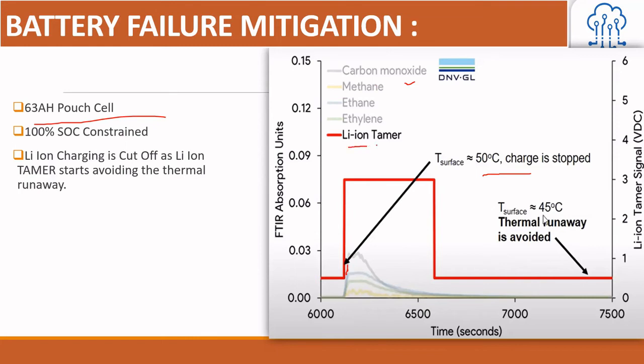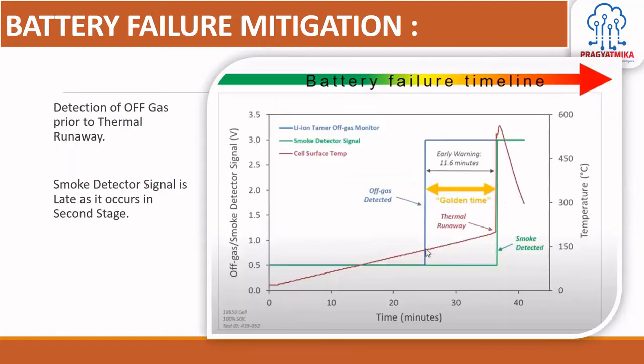the Li-ion Tamer signal, this is the Li-ion Tamer, that particular thing which I'm talking about for the off-gas event detections, could be started, and it cuts off the battery pack from the charging or discharging systems. So the thermal runaway could be avoided at this stage, and the surface temperature could be lowered to 45. So 45 degrees centigrade is quite common for battery packs, but if it is beyond 50 degrees, 60 degrees centigrade, then it will be dangerous for the cell internals. So this timer can be helpful for me.